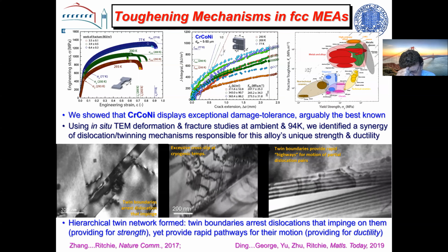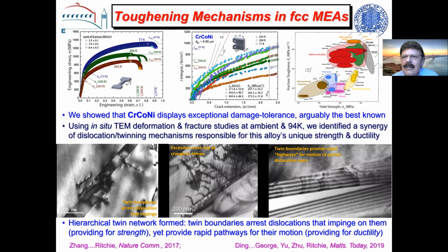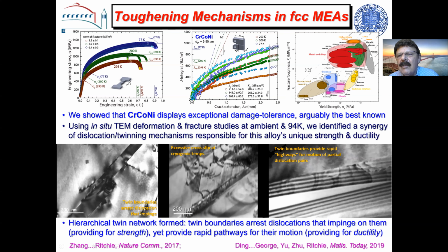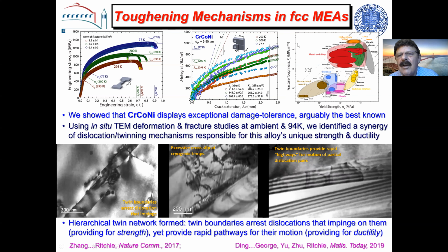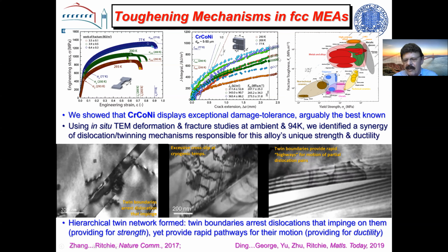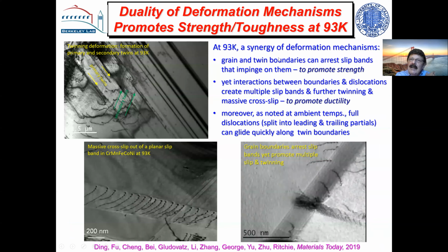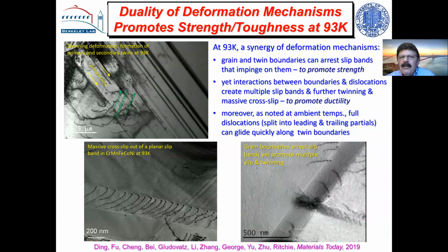And of course, these materials do have really remarkably high toughness. I mean, this is an Ashby plot here, not quite as strong as metallic glasses, but extremely high toughnesses. And these numbers are absolutely off the scale. We've looked also at lower temperatures where the maximum properties are.